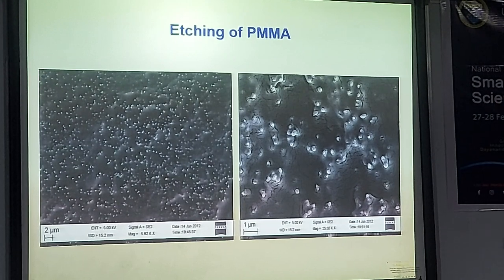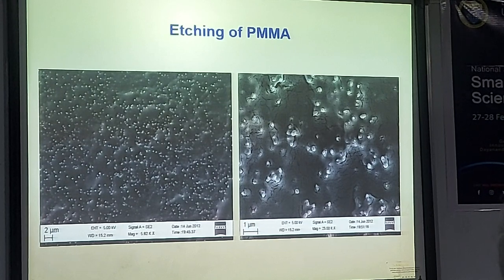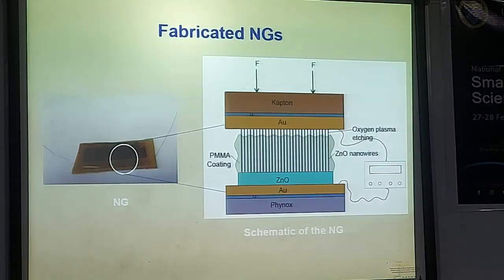And when these nanorods are synthesized, they become very delicate. So in order to make them robust, we filled them with a polymer, PMMA, so that they become strong. The top side should be made reachable for the electrical conducting layer. Therefore, the top PMMA layer was removed using a dry etching technique. So that's how the top side looked. And on the top side, we coated a gold metal electrode and formed a generator like this.